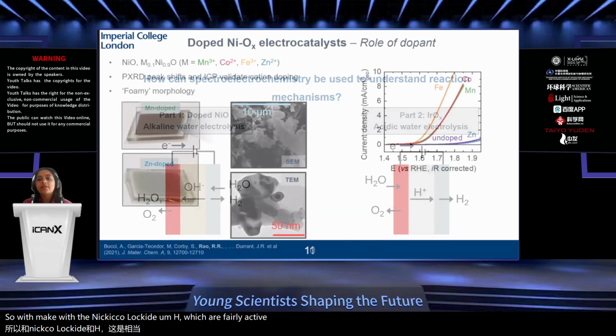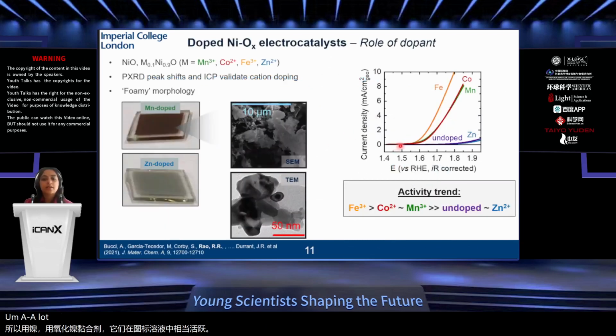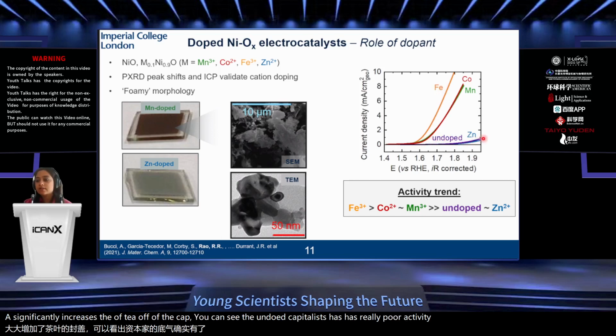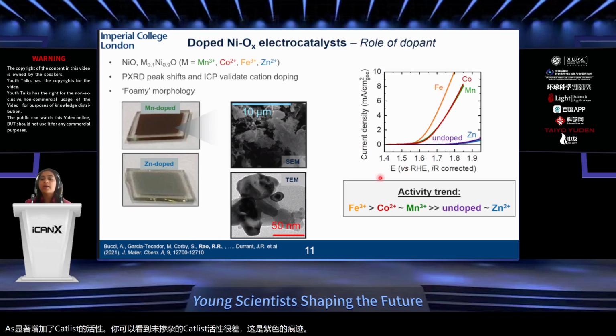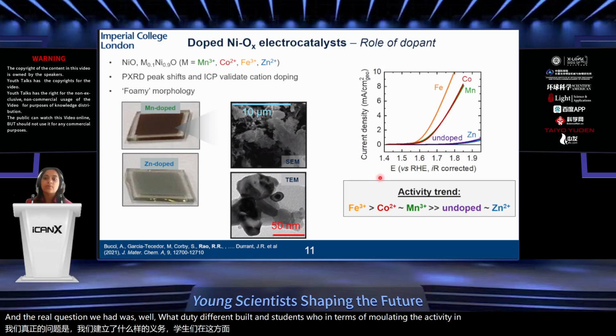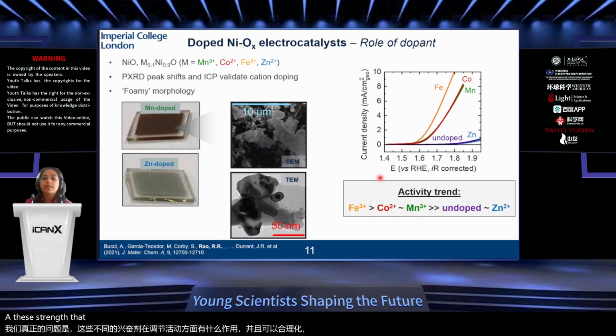So with the nickel oxide catalysts, which are fairly active in alkaline solutions, a lot of the literature has already reported that doping the nickel oxide significantly changes the catalytic activity, and particularly being able to dope it with, for example, 10% iron in this case, significantly increases the activity of the catalyst. So you can see the undoped catalyst has really poor activity. It's this purple trace here. And the real question we had was, well, what do these different dopants do in terms of modulating the activity, and can we rationalize these trends that we're seeing here?